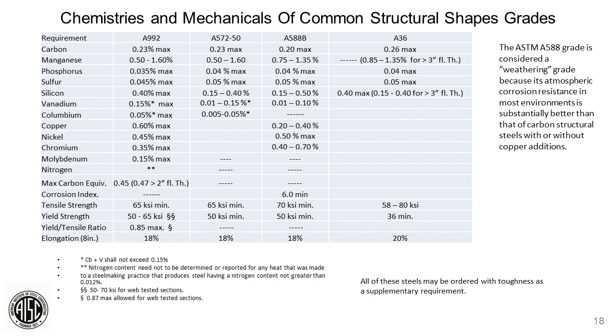I mean, I'm sure all engineers are pretty well familiar. Tensile strength, 65 KSI, typically all the way across. Yield strength, which 50 KSI is typically where all these products are produced at. Unless it's 992, which has a range, and has a yield to tensile ratio for seismic reasons. We want to have enough ductility in the steel, energy absorbed before fracture. So that's why that's written in there on that one.